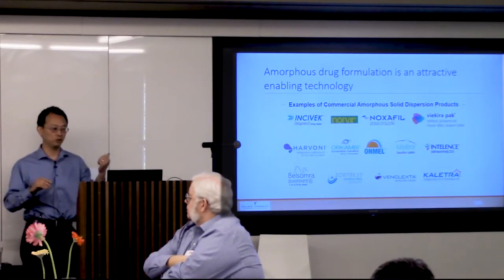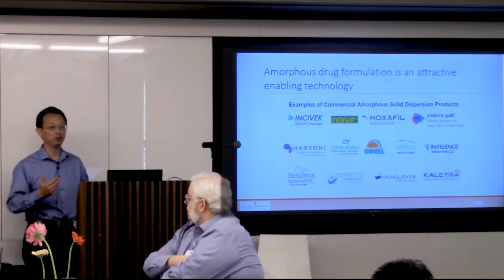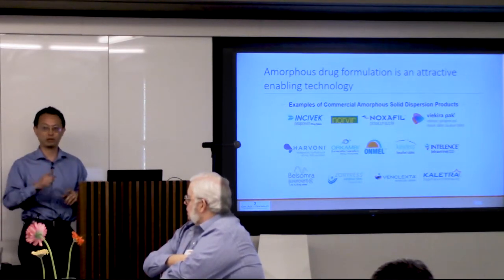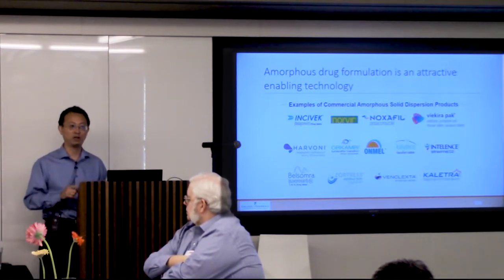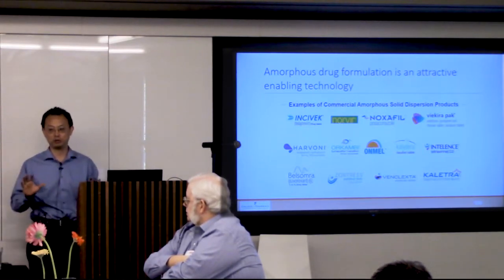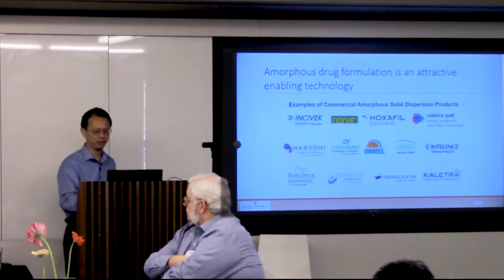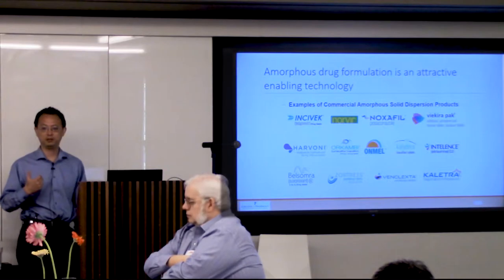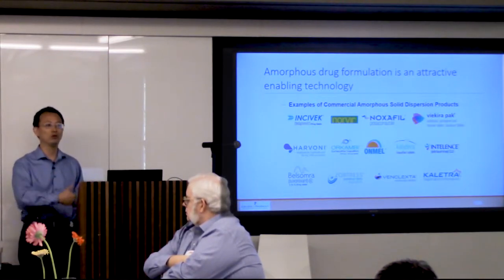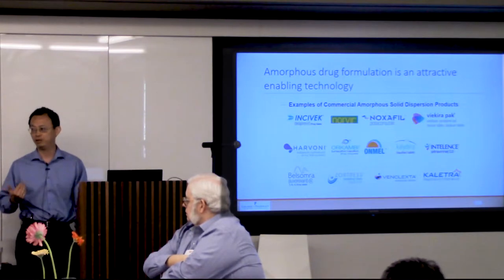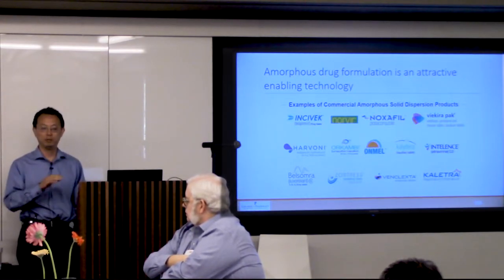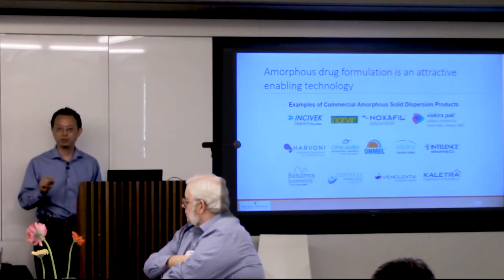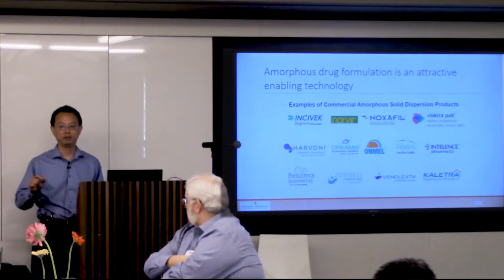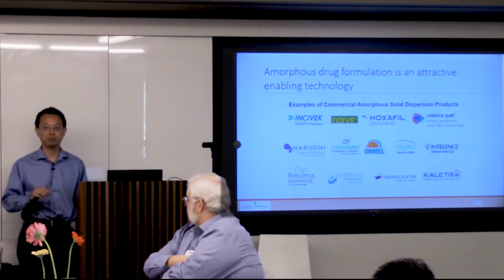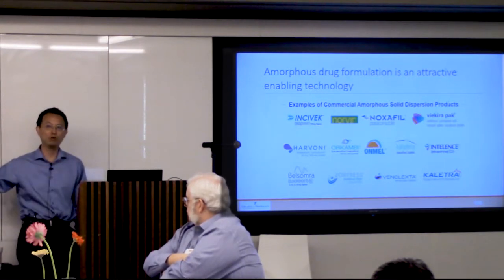I think in the early days when this glass technology came into the pharmaceutical field, there was always a concern about crystallization. But in reality, lots of drugs do not really crystallize. So once you don't have this crystallization concern during storage, it's actually a very popular technique. I think the strategy in most companies, early on, is you always do spray drying because you don't have enough drug to try another treatment. But if you look at large pharma like AbbVie or Merck, they have so much expertise, they're always trying to switch at some point. And I heard their success rate is about 50-60%, so they can switch half of the drugs over.